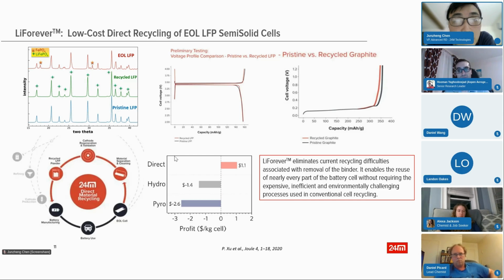Then we can demonstrate, especially for the LFP case, when we have a 3,000, 4,000 cycles LFP, we do a direct wash, and then we tear it down, we do a relithiation, then the whole cell becomes the original materials. Similar behavior we can observe from the graphite side. So SEI wash, and then with minimum cooking, then you can recover around 90% to 95% of the original capacity. So most active material can be fully recycled.